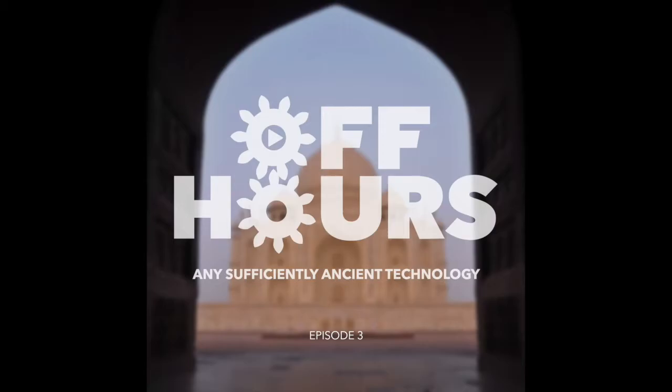Another aspect of casting that most people might not realize is you actually need to design what you're going to cast in such a way that it can be cast. Because there are certain forms or geometries where the way that gravity and centripetal forces, or even a vacuum operating, works, if you have say a very thin area leading into a very thick area and down to a very thin area again, or a whole bunch of loops of this, you might not actually get enough metal flow to fully fill what you're trying to cast.